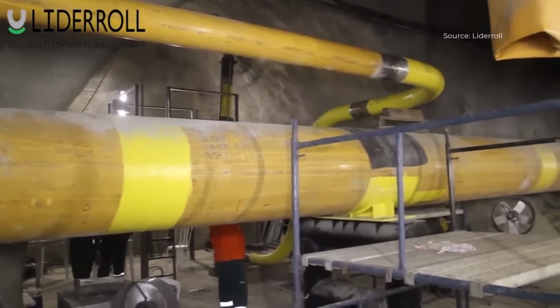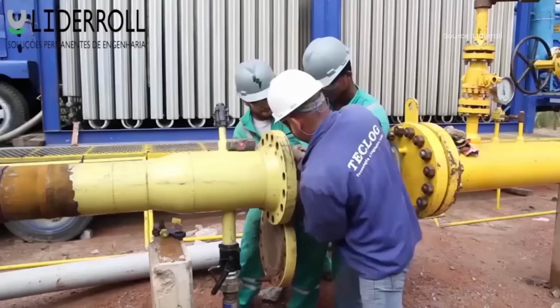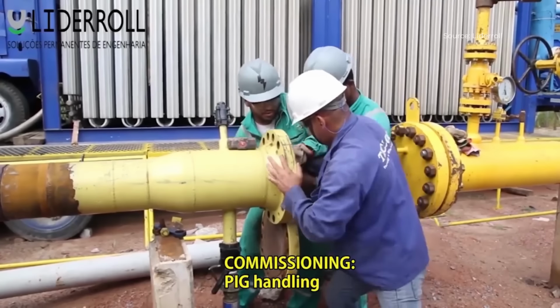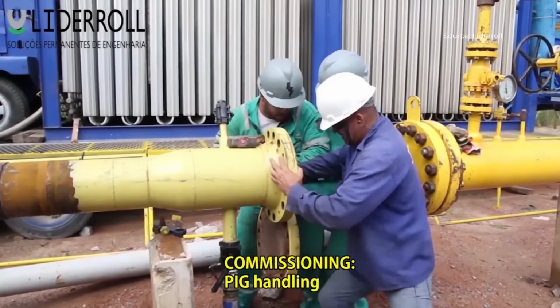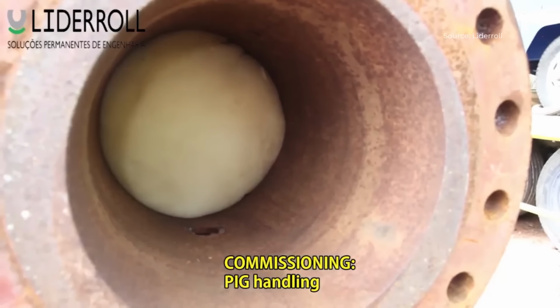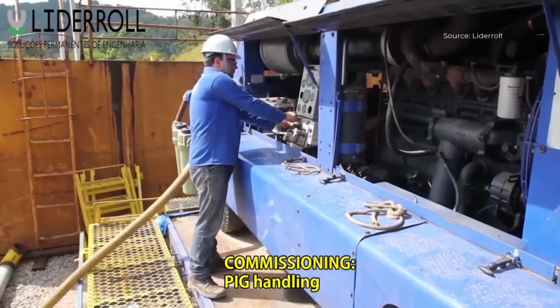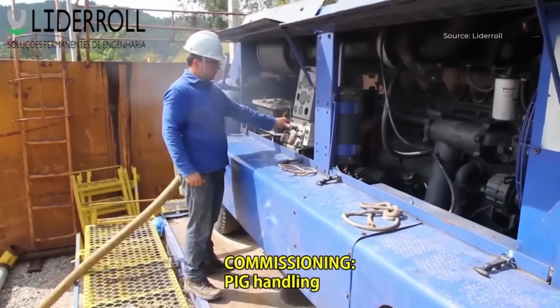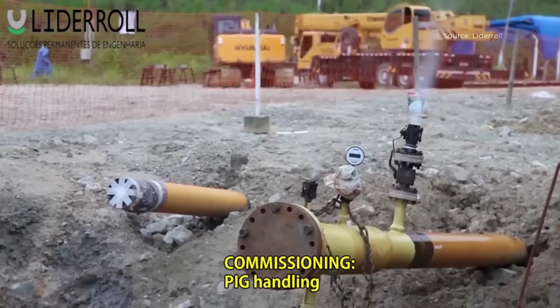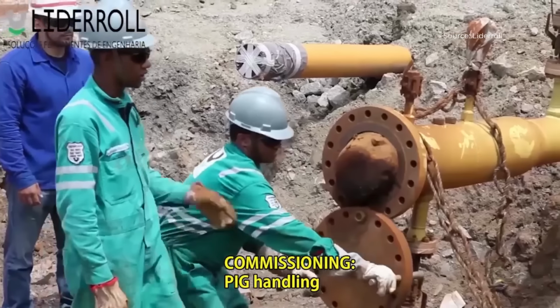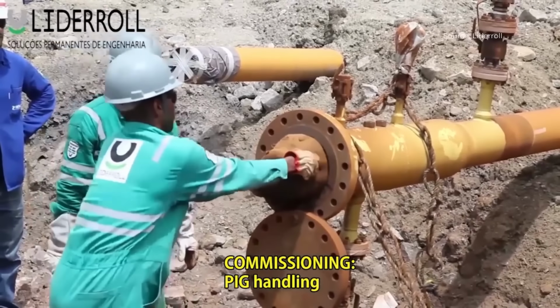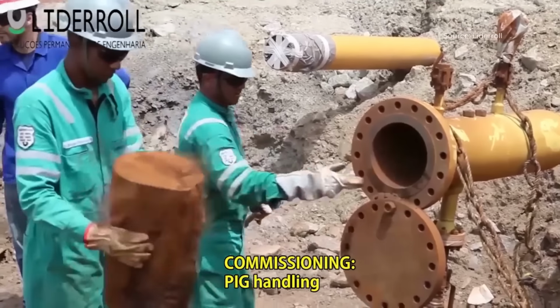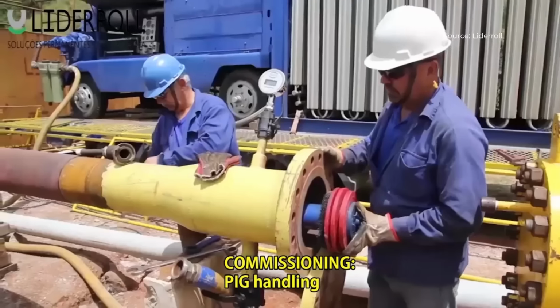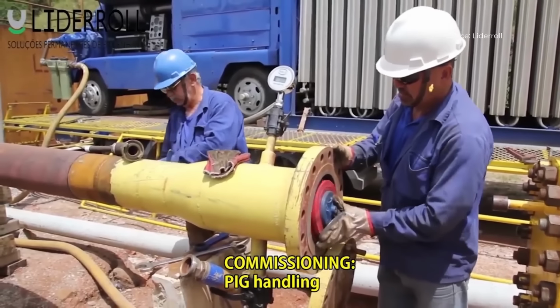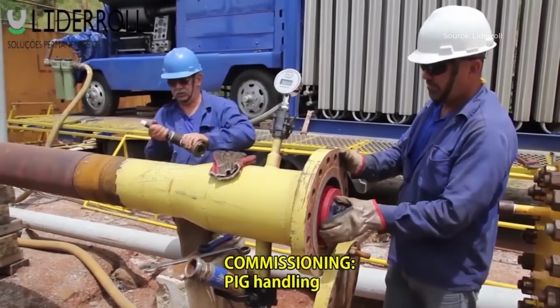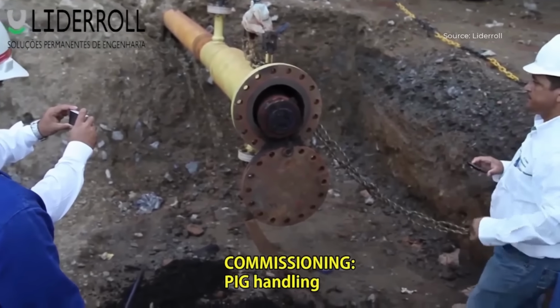When the mechanical installation was completed, the project entered the commissioning stage. The primary activity in this phase was PIG handling. Special pipeline inspection gauges, known as PIGs, were inserted into the pipelines to clean internal surfaces and verify the continuity of the line. These PIGs traveled through the entire 5-kilometer section, collecting data and removing debris, weld slag, and coating residues. After PIG, pressure testing was performed to confirm leak tightness and mechanical strength under operating conditions.